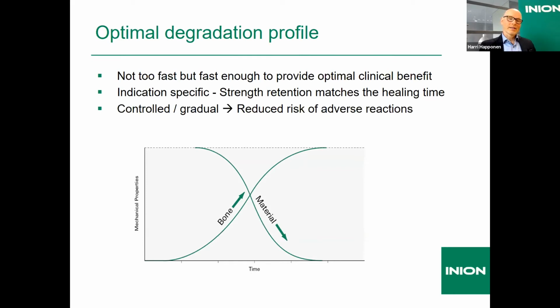And it's always important that the properties of the implants are indication specific. That's why Inion is not using only one polymer for all their implants, but we are selecting different composition of blend mixture of the polymers for different applications. For example, for the pediatric craniofacial procedure, you can have a faster degrading polymer because the skull is growing, and also the metabolism of the young patient, pediatric patient, is faster. They can tolerate the higher rate of degradation byproducts.